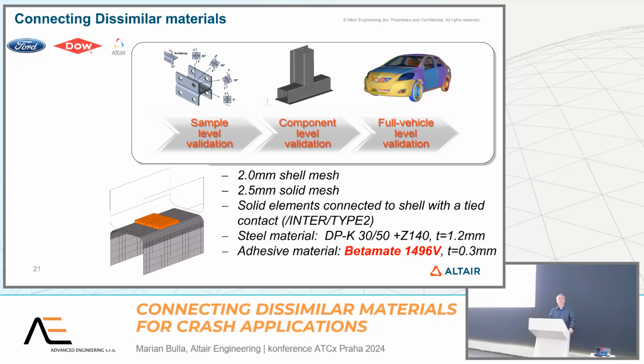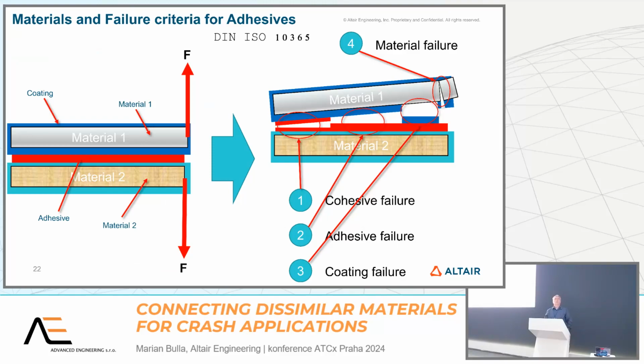Okay, how to now deal with and model all these materials and failure criteria for real applications, because in reality you do not have naked steel. You always have a KTL surface or whatever paint or coating on your metal, then you apply adhesive and so on. So in reality we have this kind of situation. Here we have material 1, here we have material 2, which is a different kind of material. This can be, for example, a metal, a polymer or composite, whatever. Or steel and aluminium, same issue. And then we have coatings, and we have the adhesive. And then we load the structure in this way.